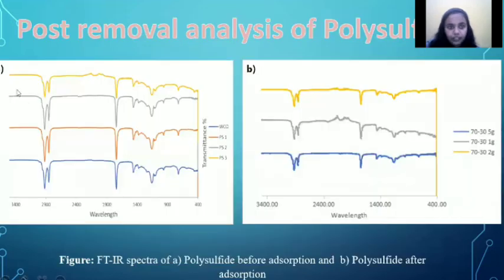As for the post-removal analysis of polysulfide, we have done the FTIR analysis in order to find out whether the methylene blue has adsorbed or not. The result shows that methylene blue has adsorbed. Compared to the previous FTIR peaks, some peaks have disappeared in the post-adsorption FTIR, and there's less noise, which shows the adsorption process is successful.